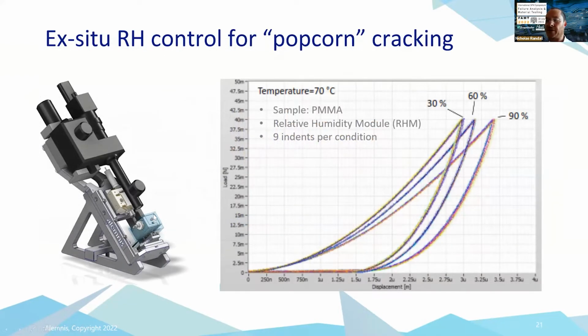We use the humidity control module for testing packaging. So typically MEMS packaging where we might have popcorn cracking. We can simulate different humidities and actually do a compression test of the whole package. So these are tests on PMMA at 30, 60, and 90% humidity.